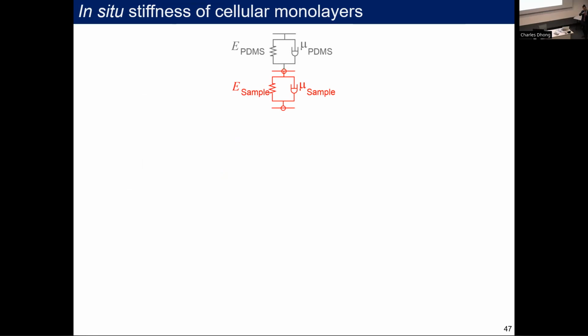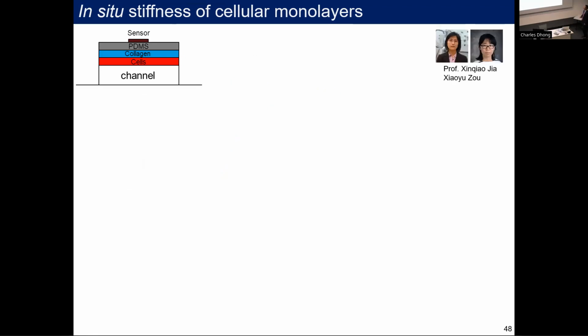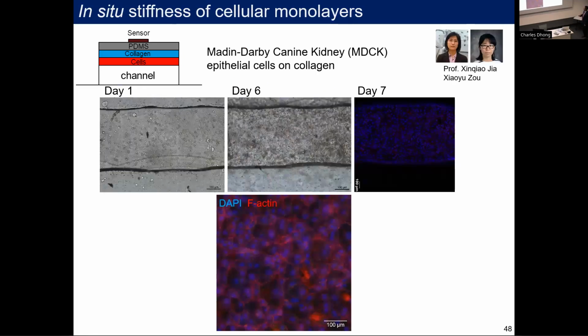So what I can do is coat a second layer inside that channel, and it should change my response. So what we do is we take that microfluidic channel and we coat it with little discrete islands of collagen, and then we grow a monolayer of cells inside. Working with the Jia group, they grew some MDCK cells, which form a monolayer. This is where the cells are seeded, and then they reach confluency by day 7, which you can see, they're all nestled up against each other, forming a single layer.